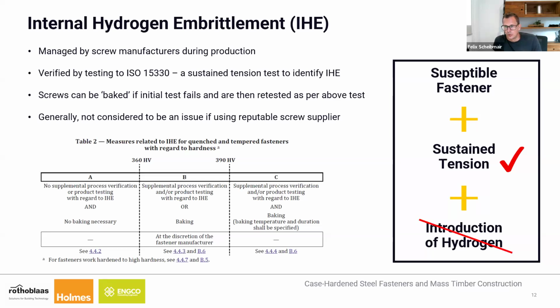If you then get a failure there, you would bake that batch and then retest it. If you retest it and it fails again, then that batch wouldn't be released, so you would essentially discard it. If you're above 390, then you're essentially always baking. The baking helps in terms of diffusing the hydrogen atoms, so it reduces the concentration of the hydrogen atoms in certain parts of the screw, and allows for those screws to still be released or pass that ISO test. The important thing here is that, like I said, it is really out of control of the end user.